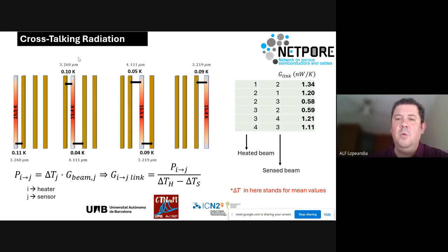It's a very small thermal conductance. And of course, the distance between the beams is not homogeneous. The two at the limits are more or less the same. In the center we have around 3, 4, 5 microns depending on the design, and at other places much smaller. This is the value that we have to take into account: the thermal conductance between beam 2 and beam 3.